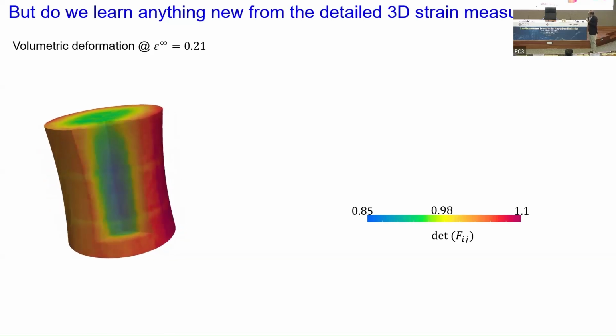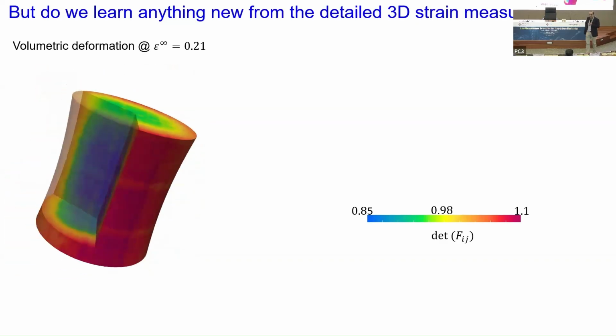If you look at this, you're going to see that something rather strange has happened in the specimen. We have pulled the specimen in tension. And what has happened is that there is an outer shell that has formed where you're getting a 10% increase in volume, and an inner core where you're losing 15% in volume. So this is bizarre because you've pulled this in tension. Normally, if you pull it in tension, you either get no volume change or you get an increase in volume. But what we seem to have got is this mixture of volumetric gain and volumetric loss inside this rubber. But everybody would have told you that silicone rubber is an incompressible material. How is this possible given this kind of measurement?